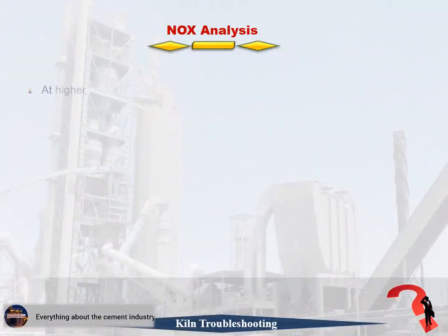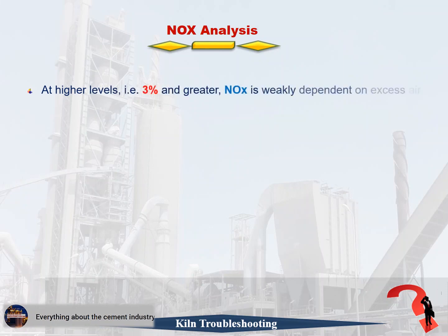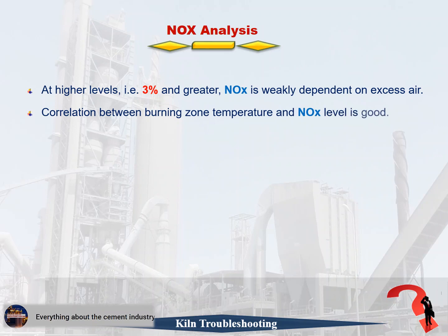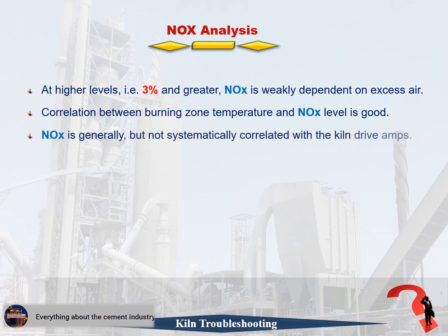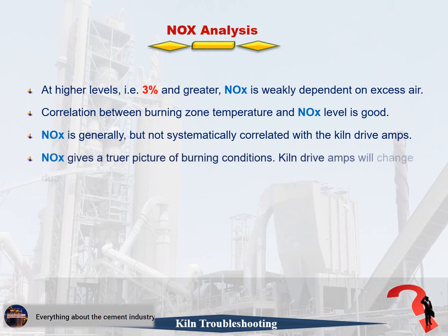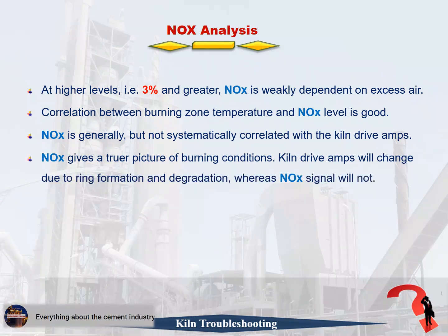Sixthly, at higher levels, 3% and greater, NOx is weakly dependent on excess air. Seventh, correlation between burning zone temperature and NOx level is good. Eighth, NOx is generally, but not systematically, correlated with the kiln drive amps. Ninth, NOx gives a truer picture of burning conditions. Kiln drive amps will change due to ring formation and degradation, whereas the NOx signal will not.